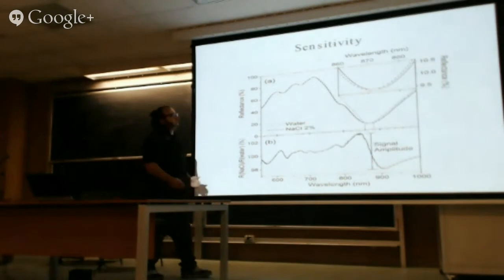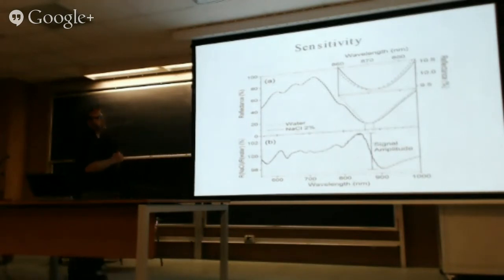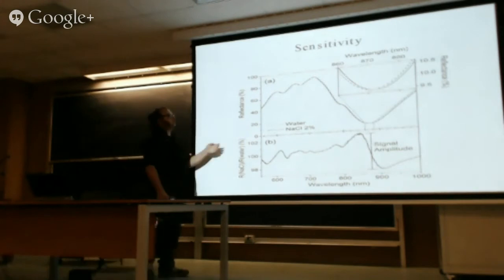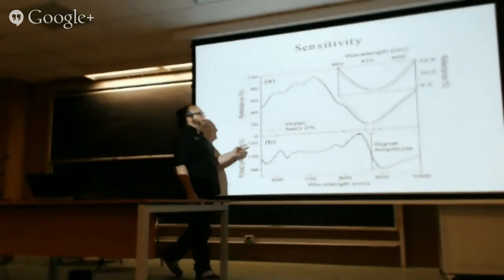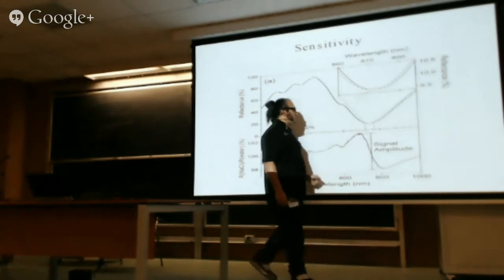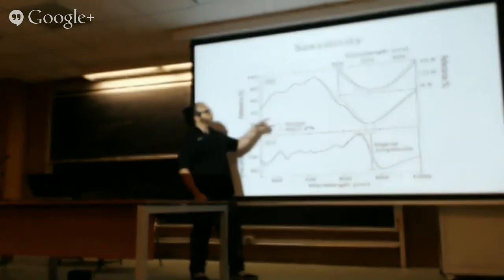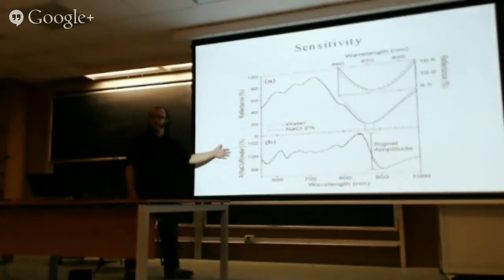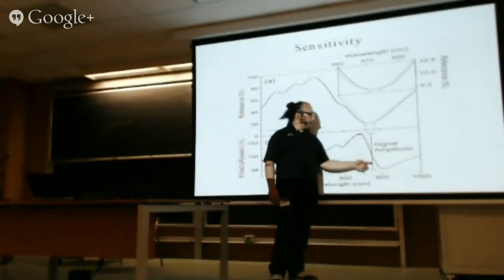This is our study concerning the sensitivity. In this case, we considered water and water with salt with a concentration of 2%. Here you can see the shift that is quite small, but if you use the ratio between these two signals, you can achieve this kind of structure that is a relative measurement, and this is our signal amplitude.